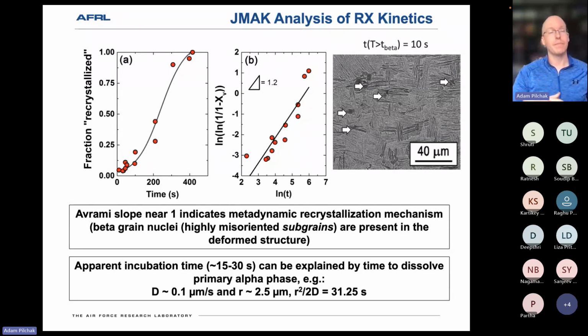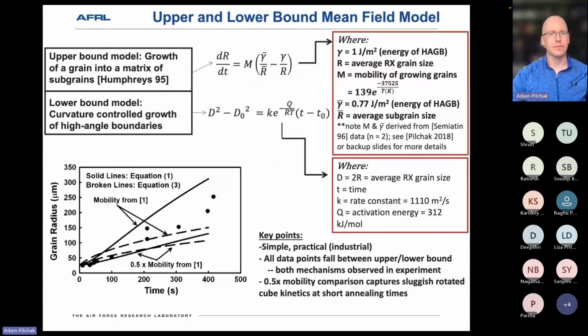But as I mentioned earlier, as you heat the material above the beta transus, the alpha phase is dissolving. And then once it dissolves, those beta grains become unpinned and are free to grow. And of course, that dissolution process takes time, even when you do go above the beta transus. So we did some quick diffusion calculations based on some of the sizes we measured for samples that were held just below the beta transus to estimate how long it would take for the remainder of that primary alpha to dissolve once you went above the beta transus to then unpin the beta grain boundaries, and that was of the order of around 30 seconds or so.